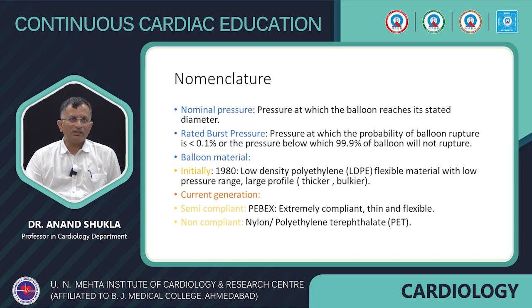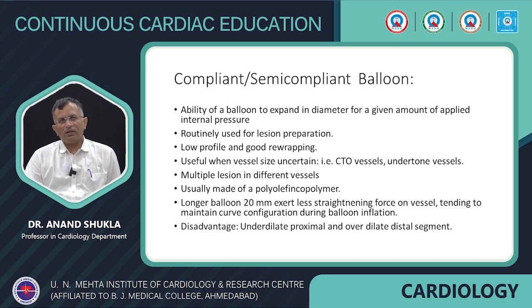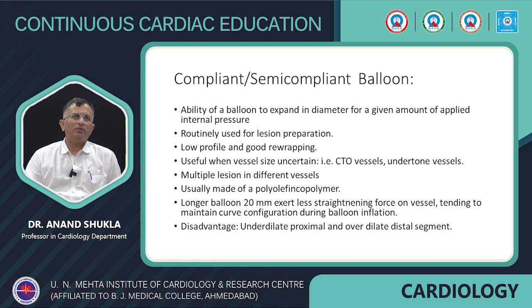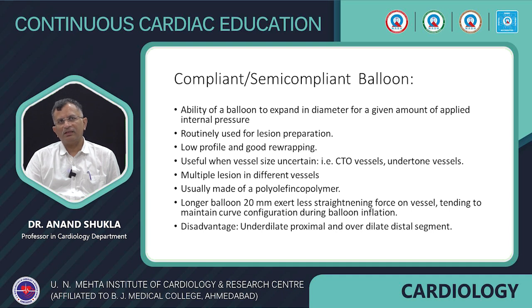Regarding balloon material: initially stiff materials were used, but in the current generation there are PEBAX-based semi-compliant balloons that are extremely compliant, thin, and flexible. Nylon or polyethylene terephthalate (PET) material is used for non-compliant balloons. The term 'non-semi-compliant' or 'compliant' is a misnomer — all balloons are technically semi-compliant. The compliant balloons are less common. The semi-compliant balloon's key property is its ability to expand to a diameter for a given amount of applied internal pressure.